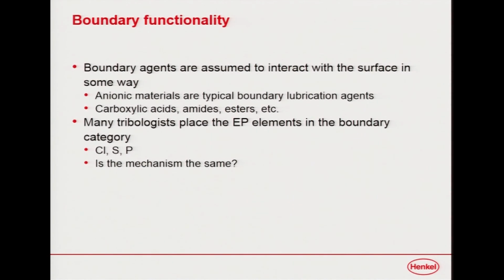Boundary functionality by Bowden and Tabor is defined by the way they interact with the surface. Typically, anionic materials, since metals are generally positive. Metal oxides have some residual positive charge. So you get things like carboxylic acids, amides, esters, anything with a double bond on it will interact with a metal surface and will actually fixture and in some way assemble itself on the surface. We have something in tribology that we call EP, and EP stands for extreme pressure. EP is a very challenging regime to work in, and that's where I chose to insert myself into the science of chemical tribology. I said, well, Bowden and Tabor couldn't figure it out, maybe I can.